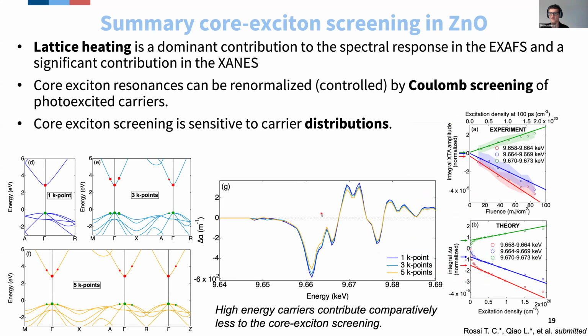Then the other thing is we found out a nonlinearity in the signal. So the amount of blue shift you get actually saturates as you increase the excitation density. And we found out that the reason why there is this saturation is because not only do you need to account for carrier densities in your simulations, but you also need to account for carrier distributions. This is very nicely illustrated here by the theory where you fix the excitation density of your system, and you perform calculations by putting carriers further and further away from the high symmetry points. So here you populate 1 k-point, 3 k-points, and 5 k-points in reciprocal space, but the carrier density remains the same between the three simulations.